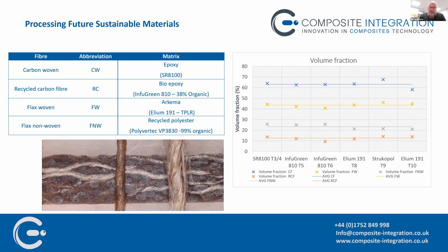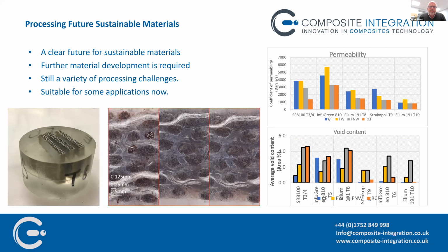And so we took all these materials and assessed them against our process map, which includes things like moisture contents, volume fraction, void contents, flow rates, viscosities, measuring all these things and trying to compare the materials against reference points. That was a pretty wide range of work with quite a bit of microscopy in there, looking at final void contents, final permeabilities. With organic fibers, we get moisture absorption, we get resin absorption. And so some of these areas we're going to need to understand in depth to be able to advise our customers in how to use these materials and for which applications they're particularly relevant.